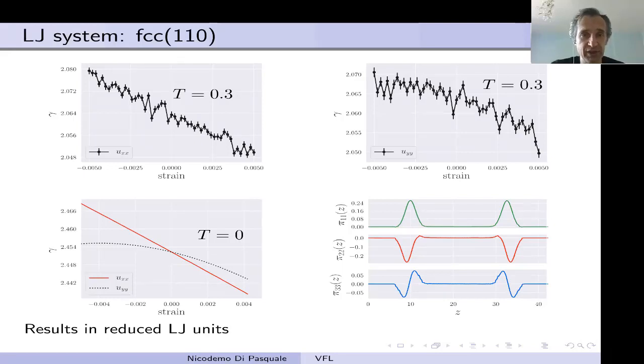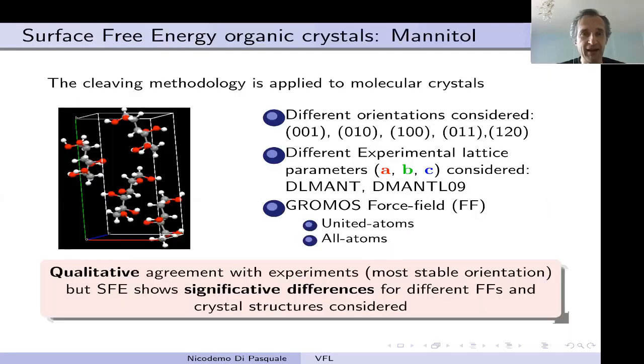I'm not going to spend time describing it, so let's just go on to the next slide, please. What we have done, which is more relevant to actually measuring surface properties for VFL, was to look at the test system mannitol, which you saw in Vikram's talk, and look at different surfaces and measure surface energy using our so-called cleaving method. And for a long time, we actually tried to understand what was happening, because our results were quite different from what Imperial was getting from their measurements.